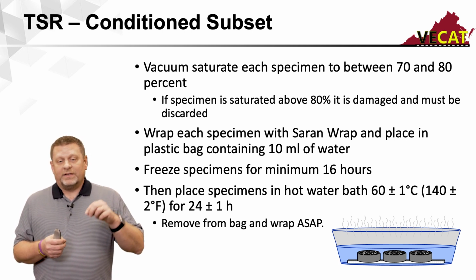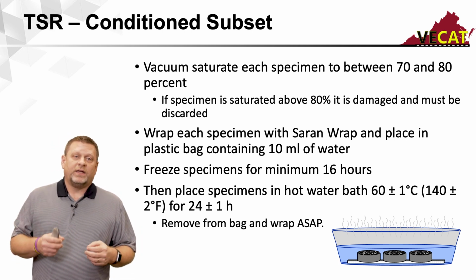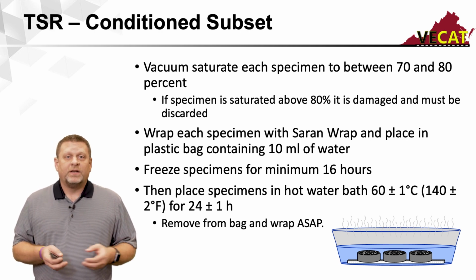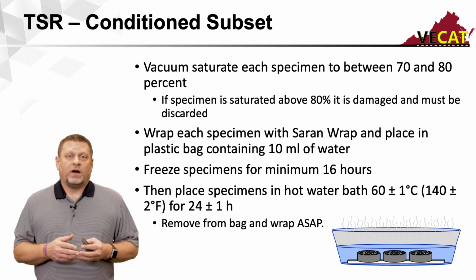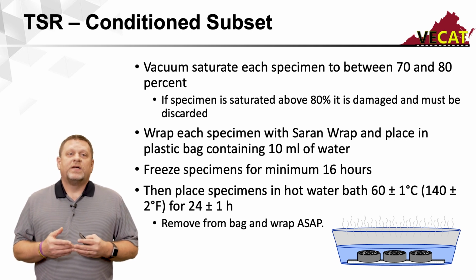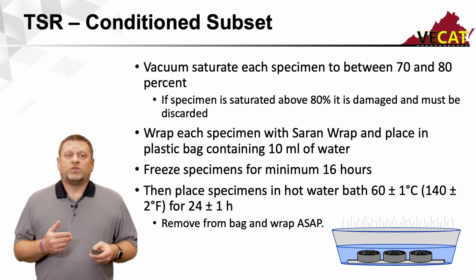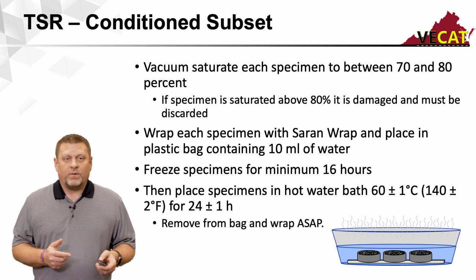What I recommend is just dunking your specimen really quickly in this hot water. Once that happens, the plastic basically falls off your specimen, and you can just set your specimens in there. So we'll have all 3 specimens in this hot water bath. They'll soak in this hot water bath for 24 hours plus or minus 1 hour.